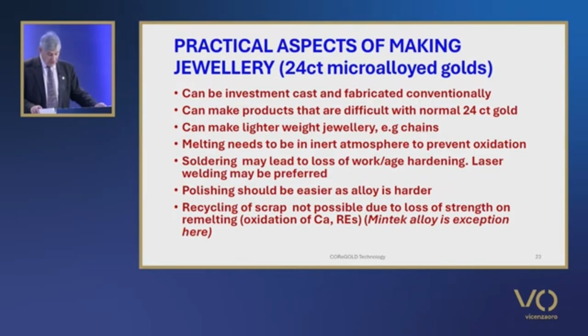As with normal 24-carat gold, soldering must be consistent with local national laws, and in some countries, use of a lower 22-carat solders is allowed, although there may be limits on the amount of solder used. However, another factor is the temperature of soldering, which can lead to a loss of work and age hardening in the vicinity of the soldered joint. Laser welding may offer a better solution there. There are also very low melting point 22 karat gold solders, I might like to remind you, and one solder has a melting point of only 361 degrees Celsius. Polishing should be easier than conventional 24 karat golds as they are harder. And Bernardin, in his paper at the Santa Fe Symposium, noted that castings require procedures similar to those for platinum.